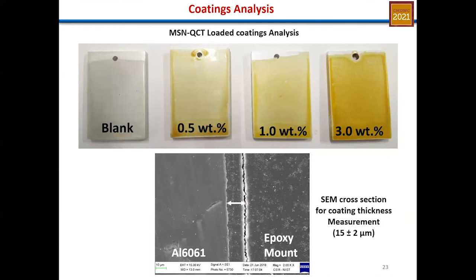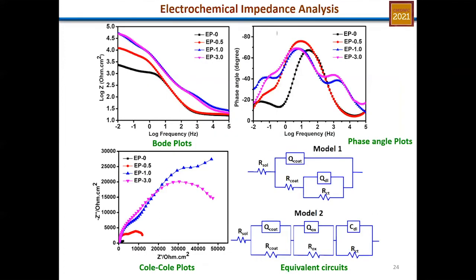We prepared the coatings using the dip coating method, and we loaded different weight percentages from 0.5 to 3. We also found the thickness to be 15 plus or minus 2 micrometers. With this, we carried out the coating analysis. From the electrochemical impedance analysis, from the Bode plot we could observe that at the lower frequency we have a larger impedance, and phase changes also occurred. The diameter of the Nyquist plot also increased with increasing concentration, but we had the maximum efficiency at 1%.